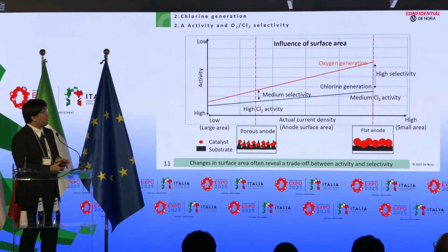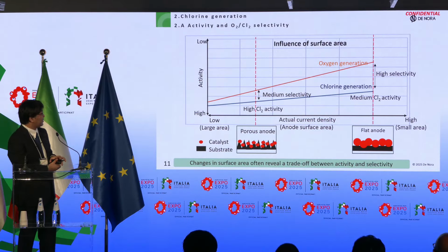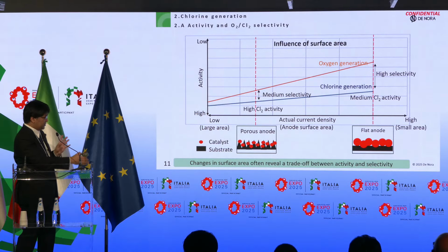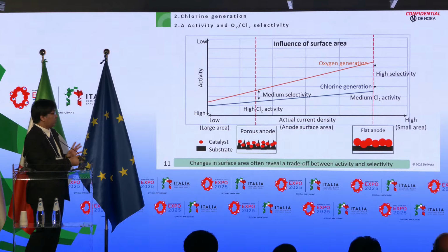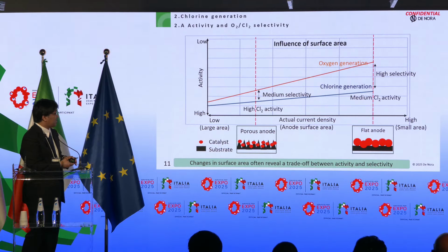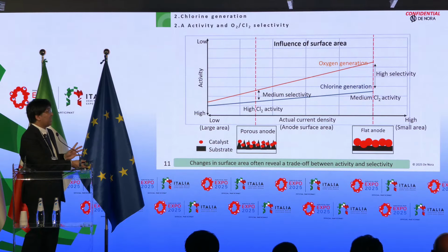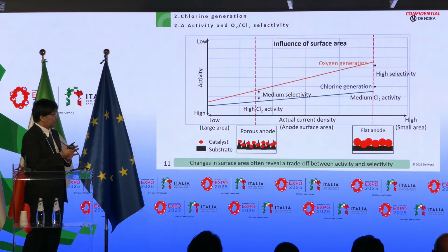And sometimes chlorine generation activity and chlorine selectivity show a trade-off relationship. The reason is, let's consider the same catalyst with different surface area. In case of small surface area, it shows very high actual current density. So chlorine generation activity is low, but oxygen overvoltage is too high, so chlorine selectivity is high.